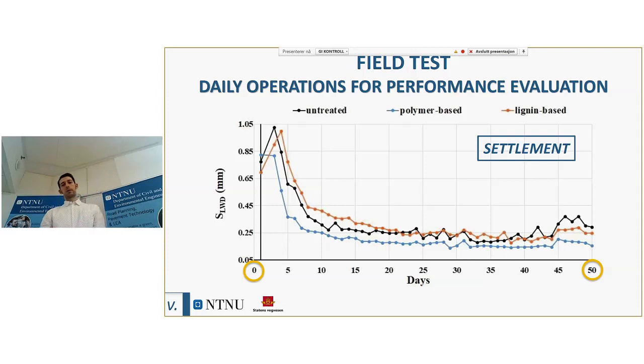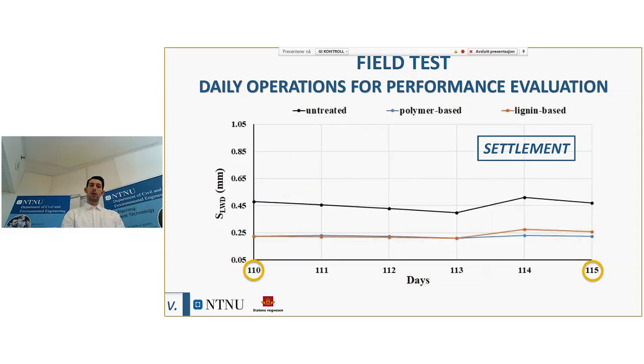Similar results can be inferred regarding the settlement. These are the settlements, again assessed by the lightweight deflectometer during the first 50 days. Again, the settlements connected to the use of the polymer-based additive are the best ones, since we have the smallest permanent deformation values. And when it comes to the permanent deformation values after 4 months, again both the lignin-based and polymer-based additives perform very well, similarly, and in any case much better than the untreated material.